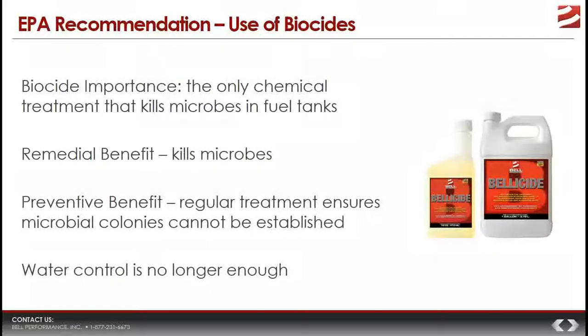If you have a low level of biocide consistently present in the fuel, that prevents microbes from getting established in that tank, and thus it becomes a preventive way of treating that tank as well. And this is a radical departure from the traditional rule of thumb that the industry had really held for years. I mean, the school of thought was if you kept the water under control, if you stayed on top of water problems, you would not have microbe problems.